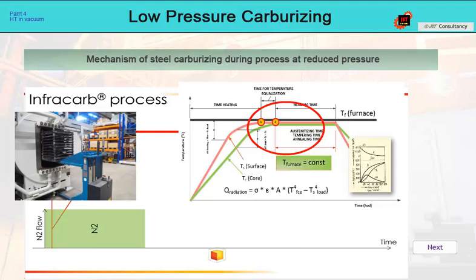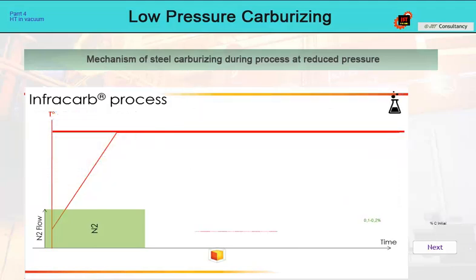Only when it can be assumed that the entire batch is at the same temperature can the carburizing begin. Proper heating of the batch is important because the carburizing gas decomposes catalytically, depending on surface temperature, in contact with the steel surface, and in order for the carburizing to take place evenly in the full cross-section, the parts must also be at the same temperature. The default amount of carbon is usually 0.1 to 0.2%, but we need 0.8%. We will achieve this by the following steps.